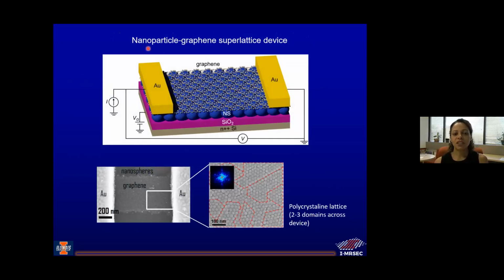Okay, so we have a device that looks like this. Again, just the nanoparticles with graphene on top, contacts on either end, and we put a current across it, measure the voltage, and there's also the backgate, which is just this capacitively coupled silicon here. Okay, here's an optical image of the actual device, and here's a close-up showing these kind of polycrystalline domains.